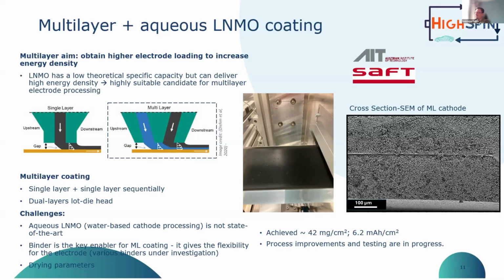Then on the right, you can see an example of a result of the multi-layer coating. In fact, you can actually not really see the transition between the two layers. This is an electrode coated on both sides with dual layer. And so we're able to achieve slightly higher loadings than what is typically achieved with a single pass coating.